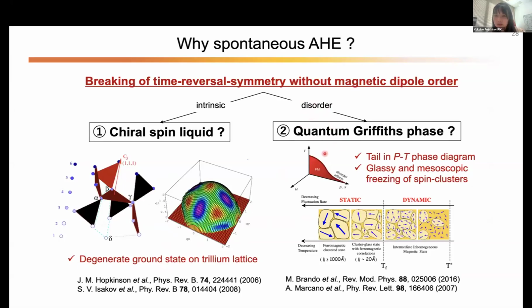Sometimes in a disordered system, the phase called quantum Griffiths phase is developed, and they have a glassy and mesoscopic freezing of the spin clusters like this, and this actually breaks the time reversal symmetry, but no one has proven this state through detailed transport measurement. So even if this is the case, it might be an interesting scenario for this compound.